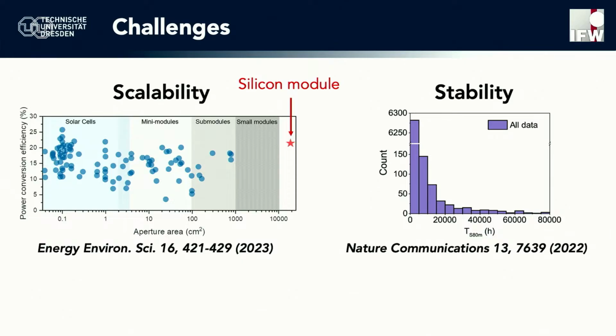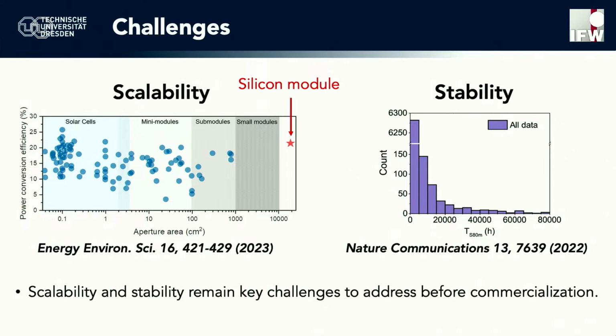The next problem is the problem of stability. So in this case, the study compared the so-called T80. So basically, how many hours did it take until the device reached 80% of its initial performance? And you can see that the vast majority of papers published, in this case more than 6,000 reports, actually report just a couple of hundred hours of stability. Only one report was able to demonstrate 80,000 hours, which is approximately 9 years. But even this is far below the 25 years that silicon solar cells are offering us. So we have to solve the issue of scalability and stability before we can go to commercialization and the market.